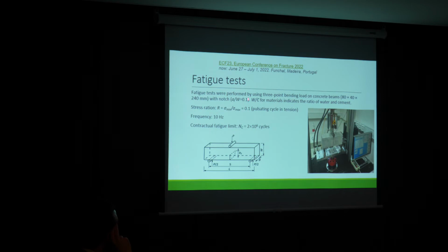The notch depth a divided by the specimen height is 0.1, the typical dimension of the specimen. And then you see here the R ratio, as I explained before, and the frequency is very low. In our case, we use a frequency of 10 Hz. There is some contribution by authors from Castilla-La Mancha.